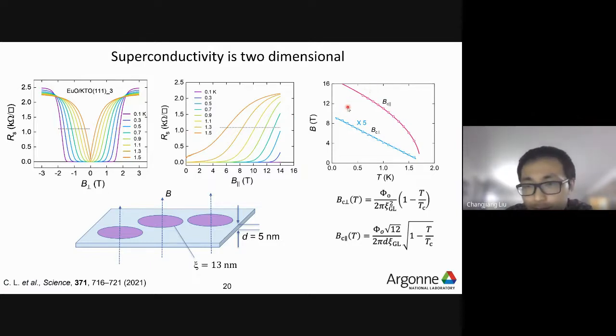So by doing this measurement, we can determine the Ginzburg-Landau coherence length, which is about 13 nanometers. And further, using the in-plane critical field measurement, we can determine the thickness of the superconductor, which is about 5 nanometers. And this 5 nanometers is smaller than the coherence length, which tells us that this superconductor is two-dimensional.